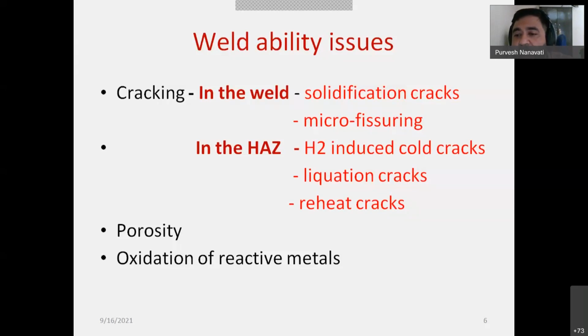Then the reheating crack phenomenon occurs most of the time in ferritic steel, like chrome moly steel, wherein during the post-weld heat treatment there will be relaxation of stresses, and the grain boundary becomes weaker, and there will be a crack through the grain boundary known as reheat cracks. Now there are other issues like porosity and oxidation of reactive metals, particularly when you're working with aluminum, nickel, titanium, which quickly form oxides like Al2O3, NiO, and TiO2.